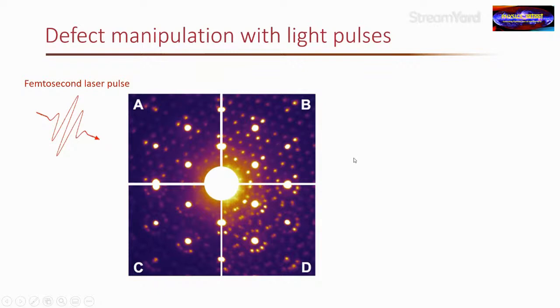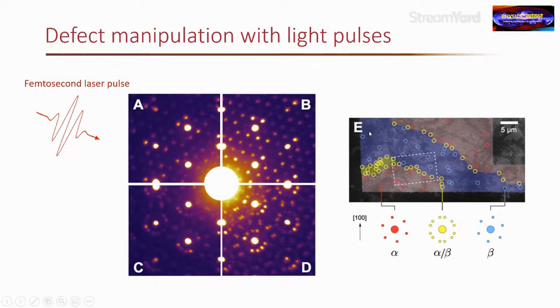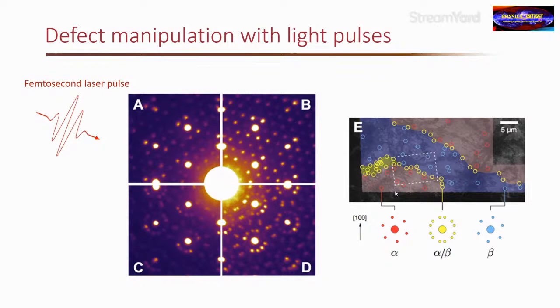Using an electron microscope, you can actually see that after shining the laser pulse, there are distinct regions: red regions with alpha diffraction patterns (counterclockwise rotation) and blue regions with beta diffraction patterns (clockwise rotation). By shining a single laser pulse we've created domains of alpha and beta configuration, roughly microns in size. Once formed, these domains are stuck and do not change as a function of time.